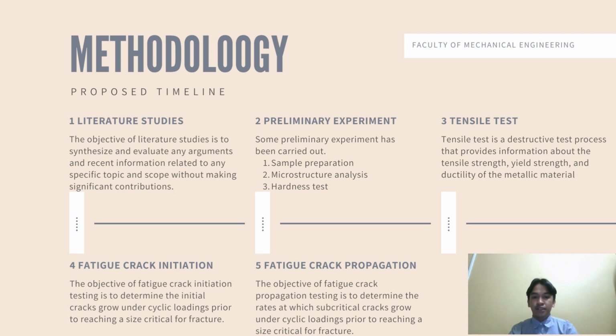The second one is preliminary experiment. Some preliminary experiments have been carried out during this final year project 1, such as sample preparation, microstructure analysis, and hardness test. Next is the tensile test. Tensile test is a destructive test process that provides information about the tensile strength, yield strength, and ductility of the metallic material. The next one is fatigue crack initiation. The objective of fatigue crack initiation testing is to determine how the initial cracks grow under cyclic loadings prior to reaching a size critical for fracture.